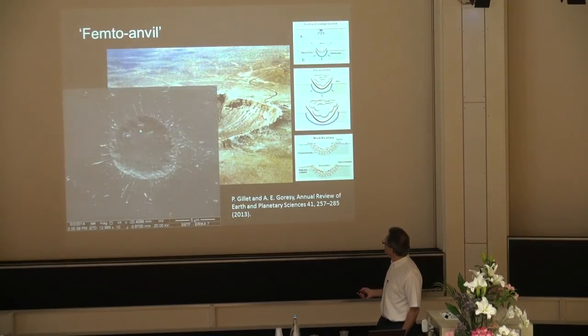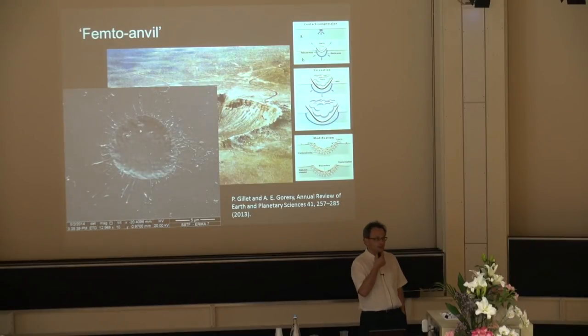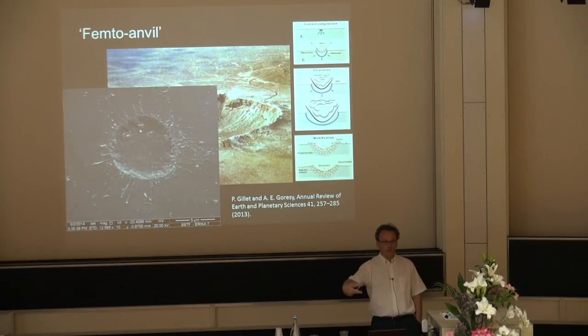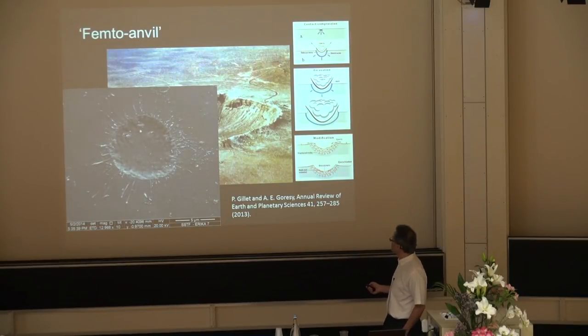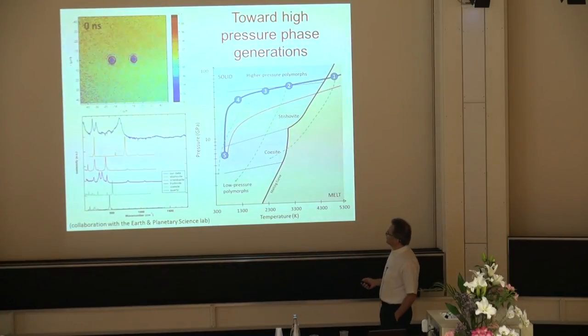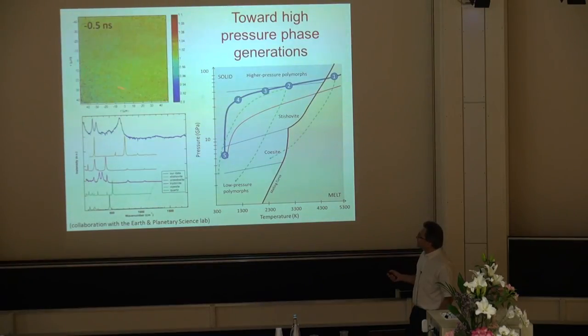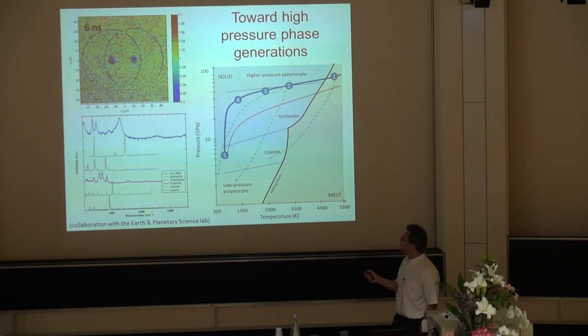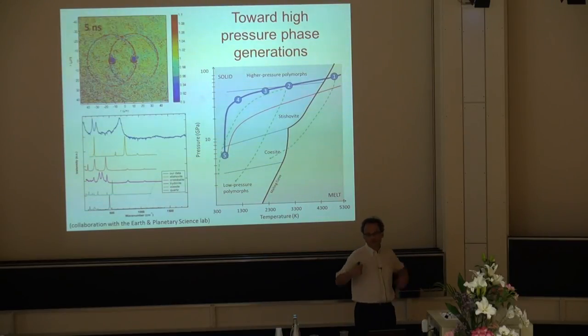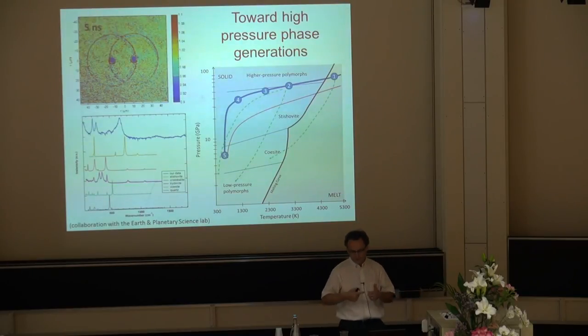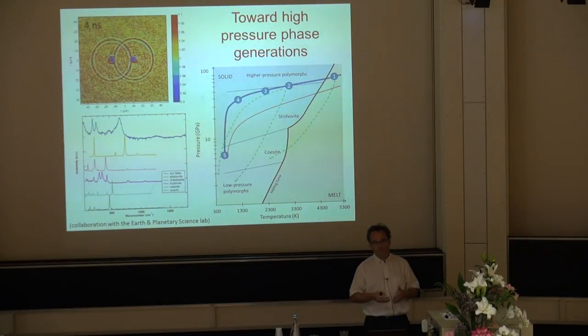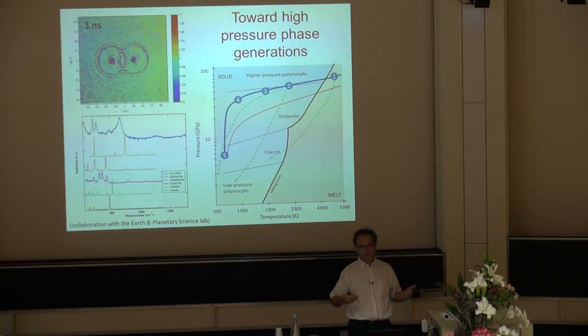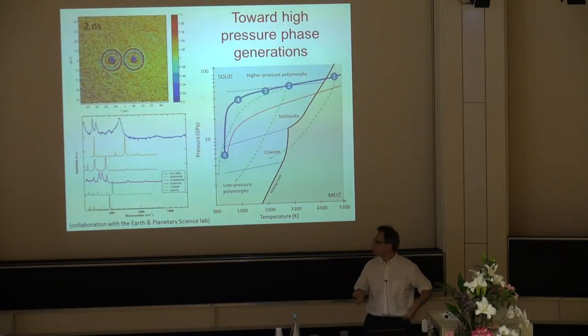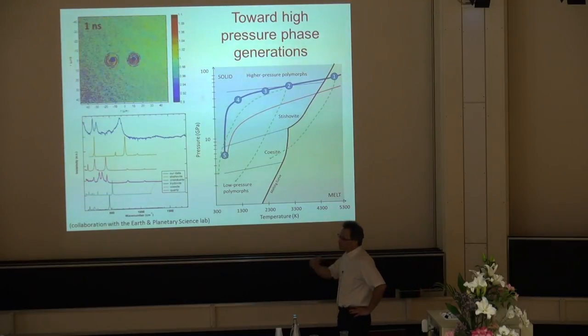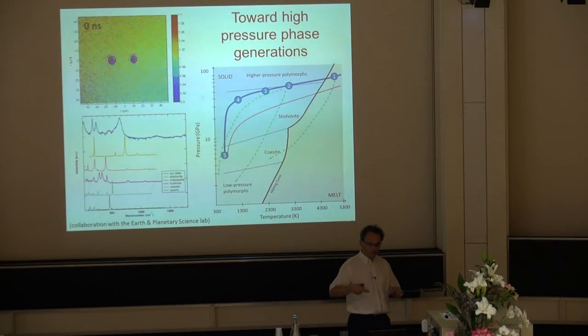So now the question is, can we recreate such conditions by firing the laser on the glass and exploring this very high-pressure wave, and how much of the material is modified? This is a collaboration with the lab of Philippe Gillet, Earth and Planetary Science Lab. I won't get into details, but here you see, for instance, experiments that Alexandros is doing, looking at shockwave propagation. Imagine we send the laser beam, and the laser beam stays for a very, very short time. Because you deposit so much energy in such a short time, you launch this shockwave from the side, and you have this wave propagating. Here it's more the acoustic wave that you see, the acoustic emissions. This is done by pump-probe experiments, where you use another laser to probe dynamically how the acoustic wave is propagating.